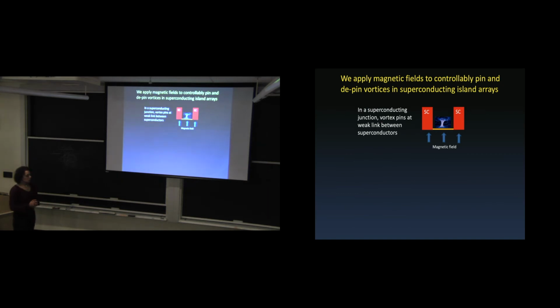Okay, so why am I talking about vortices for these systems? Well, just like before, we have this well-controlled island array, and the well-controlled island array allows us to have well-controlled vortices, right? It's another way of controlling the dissipation in the system. And that's because vortices are a phase slip, and so they occur at the weakest point in the junction, which in this case is the space right between the islands. So here, if we have our superconducting array, right, with islands and a space between them, if we apply a magnetic field, the vortex will pin between the islands at the weakest point, okay?